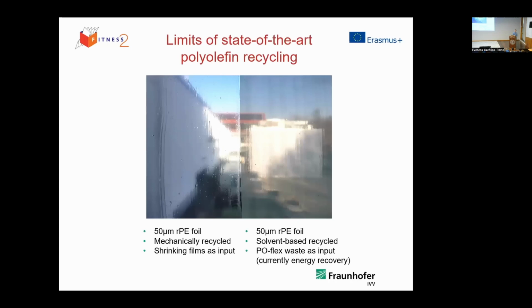And to the right, you can see a film which was recycled with a solvent-based recycling process from a PO flex waste, which is currently only used for energy recovery and not recycled because it contains multi-layers, but also residues of paper and other contaminants. So as you can see, we don't have any gels, or just very few gels in this film. And yes, it looks a little bit grayish, but it's from post-consumer material, which is currently not recycled at all. So we can see that the solvent-based recycling is a good alternative.